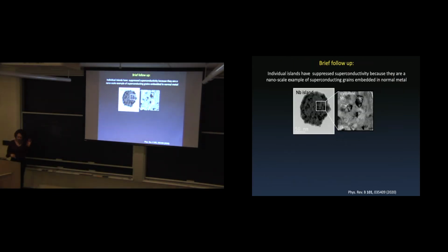Now, this is as a very brief follow-up. I'm not going to get into any detail on this, but we've done many more studies on these individual islands, because one of the implications of this result is that superconductivity in the individual islands is suppressed, right? Otherwise, it wouldn't matter how coupled they are, right? If you have one island alone and its neighbor is infinitely far away, it has no TC, right? So that means you're suppressing superconductivity on the island.